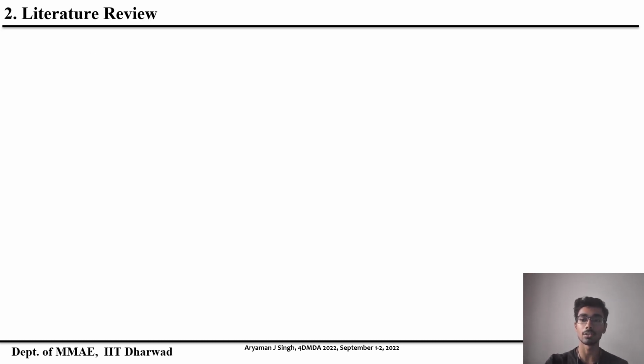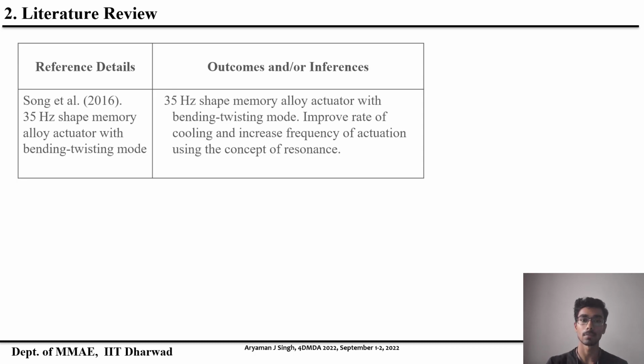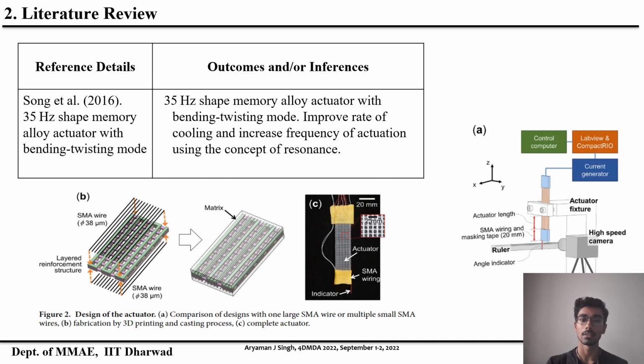Moving on, some of the literature which has proved helpful in our research is mentioned here. In this paper, the authors utilized the natural frequency of the actuator to attain maximum stroke angle out of it. They also attained up to 35 Hz of flapping frequency with SMA wires of 38 micron diameter. They used two sets of wires for two-way actuation to produce the flapping motion. They used a PDMS matrix, which is a soft and flexible material, to keep the wires in place and prevent environmental damage.